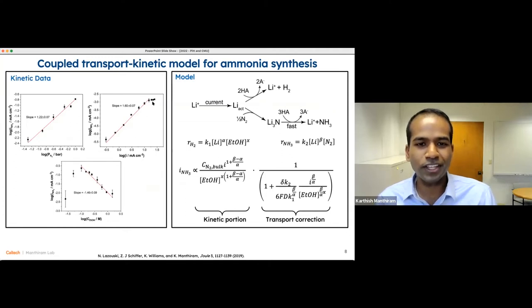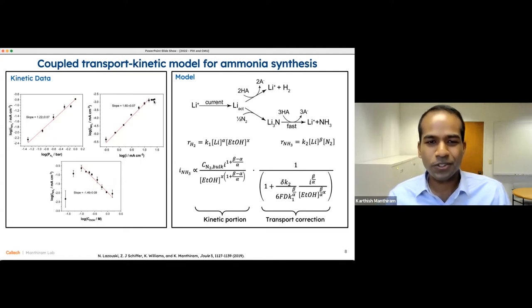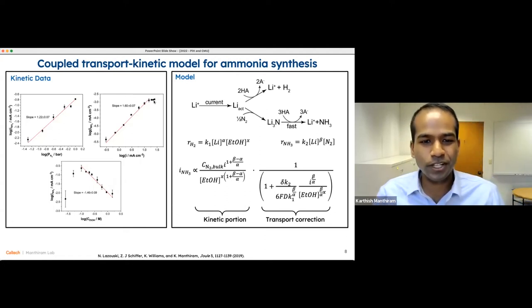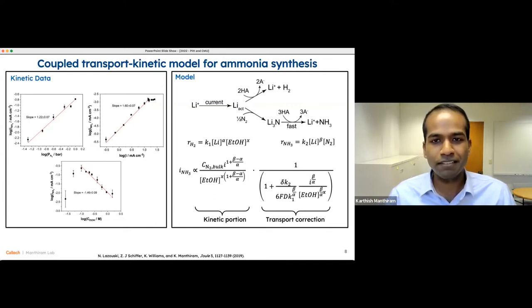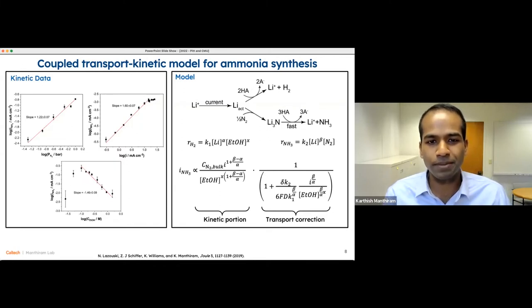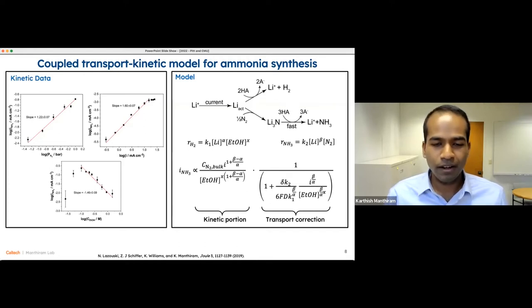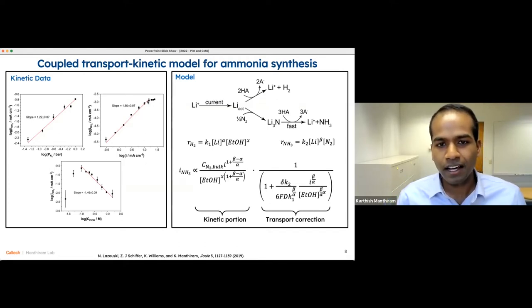So if you look very carefully at this plot, you'll see this plateau on the right-hand side. And this plateau is really the telltale sign of there being a nitrogen transport limitation, that even as we push more and more current in the system, plating more and more lithium metal, there is a physical limit to how much nitrogen can be fixed. And that's because of the transport of nitrogen to the surface. So if we look at the solubility of nitrogen, its known diffusivity, we measure the boundary layer thickness, we can see with a great deal of confidence that this limit here is in fact due to nitrogen transport.